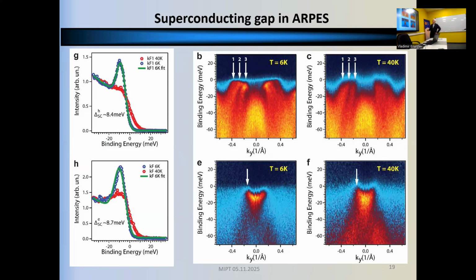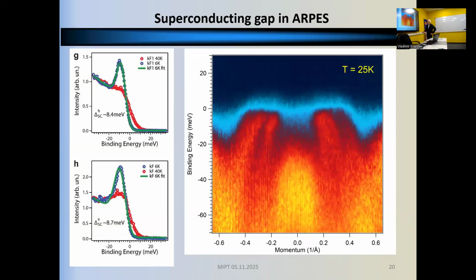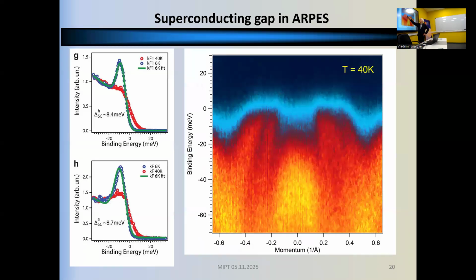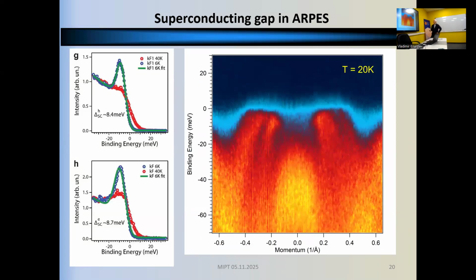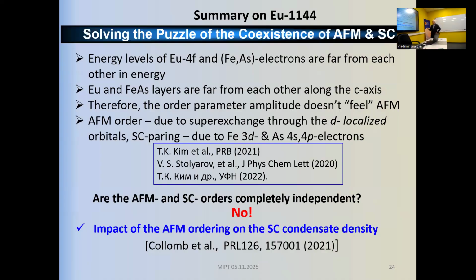But this picture, it's quite an old picture of 2021, 2022, shows how the superconductivity develops in ARPES measurements, because doing these measurements, you can notice where exactly the superconducting pairing occurs, and this can be seen here on the cross cut. At high temperature, the red curve drops down because the states above the Fermi energy are empty, so this is natural. But below the temperature where superconductivity sets in, the green curve shows that the excitations, the Bogoliubov particles, move there. And probably there is a movie which shows how the superconductivity develops upon cooling. You see that the electrons, the excitations relocate to above the gap.